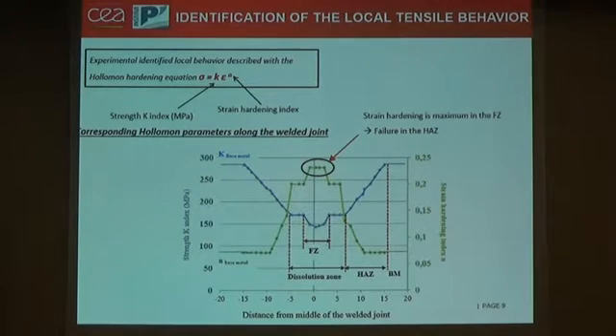In contrast, here we have 200 local behaviors, and it is not easy to implement such a model for an engineering approach. So we propose to simplify each local behavior in a set of parameters, which are the strain hardening index and the strength coefficient, which represent the two parameters of the Hollomon hardening equation. And the set of parameters is identified along the welded joints and is seen in this figure. And one more time, we have the same tendencies that we obtained with the micro-hardness profiles. So this model will be used later for the numerical simulation of toughness tests, which will be presented in this third part.